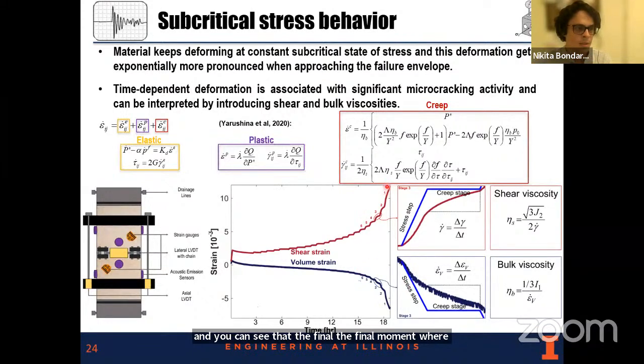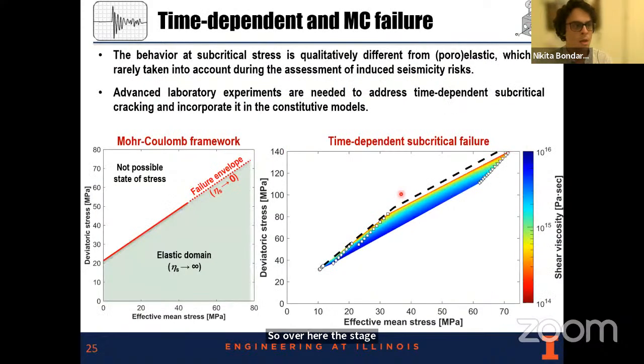So over here, stage 1 is a tertiary stage. It's just because we are almost at the failure envelope. And in this case, you can see all this time-dependent response. So if we are here, it will take 100 days to nucleate this macroscopic failure. When we are over here, the viscosity is changing by almost 2 orders of magnitude. So instead of 100 days, it will be 1 day. Again, it's just some numbers from nowhere. So in reality, if we are very close to the failure envelope, it's most likely just a matter of hours.